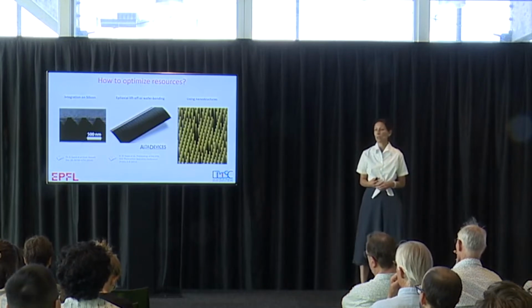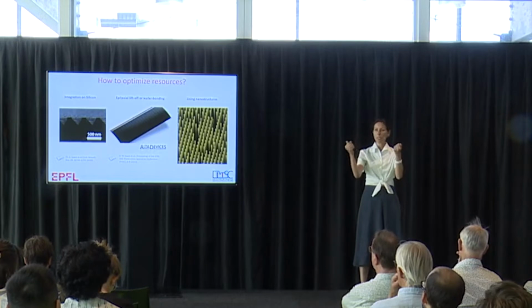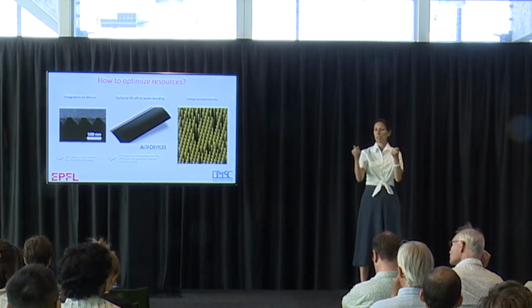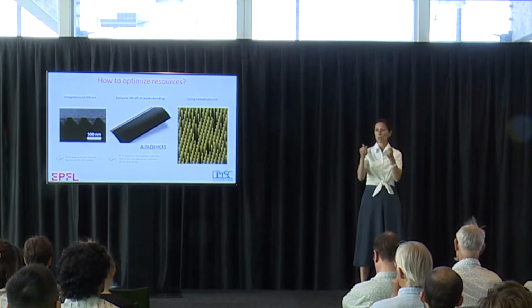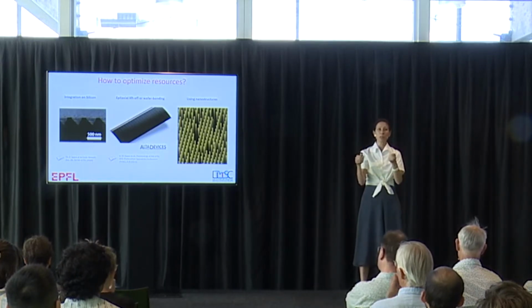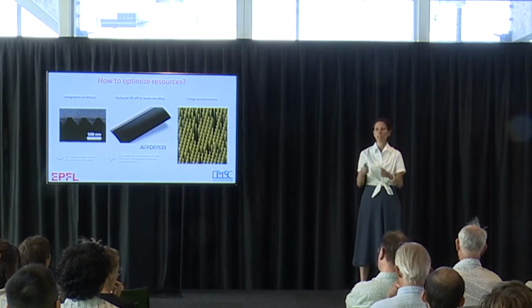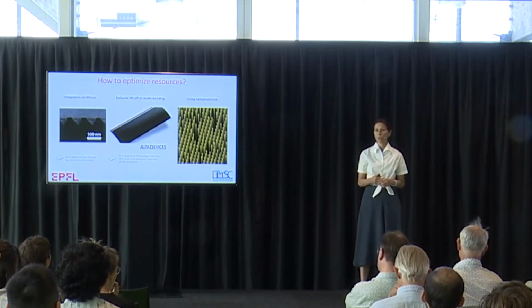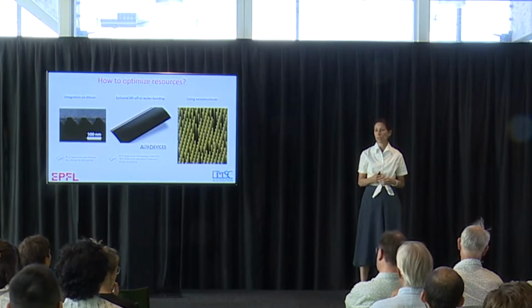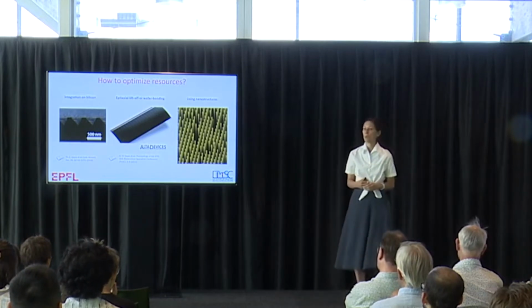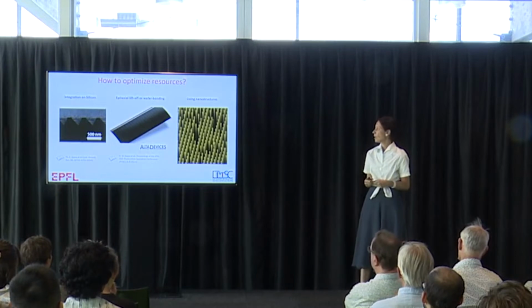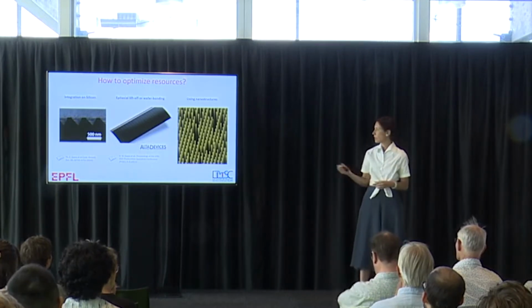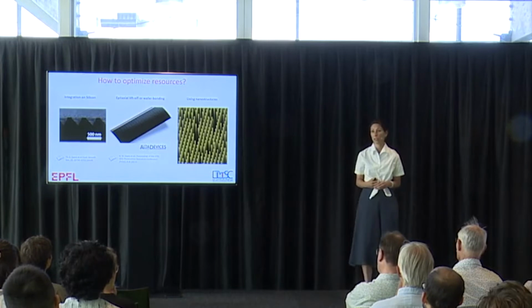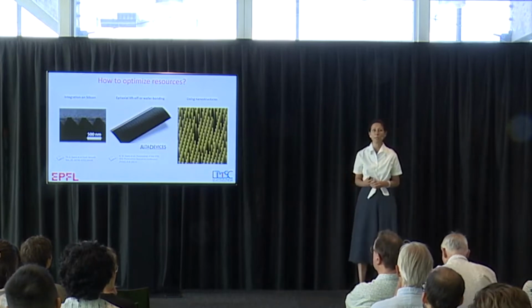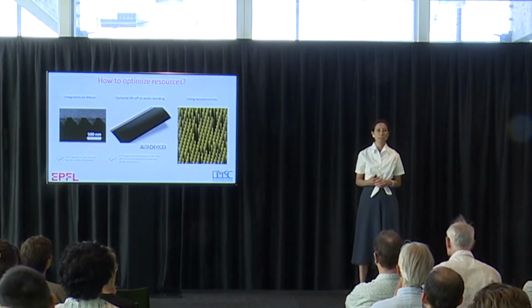It is challenging because, as you see, gallium arsenide is made of two elements, and the order of the elements plays a role. It's not just an alloy, so you need to have bonds between gallium and arsenic. And if, when you produce your material, at some point you have gallium next to gallium or arsenic next to arsenic, then your material is basically dead, because this is a high point of recombination. So it's not that easy to have gallium arsenide on silicon as a cheap substrate. Another way is epitaxial liftoff, and this was the success of Alta Devices, and the highest efficiency in gallium arsenide is from this company. Unfortunately, the company doesn't exist anymore.